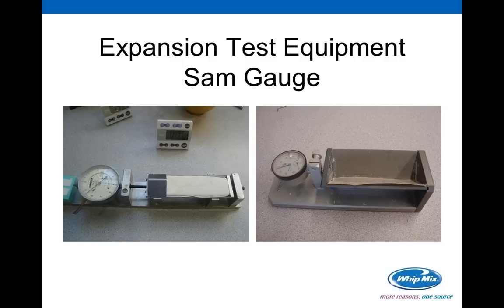Now, expansion test equipment is different depending upon where you are, and so I wanted to show you what we use here at Whitmix. We use what's called a SAM gauge. This particular gauge is 100 millimeters long from the inside wall to the inside wall, and in that gauge we place 100 grams of mixed stone. This is a good value for us because it gives us not only an overall expansion number, but because it's 100 millimeters long, if that increases to, say, 0.08, then we know that it has also moved in a linear fashion, 0.08 millimeters. Now, that's for 100 grams.